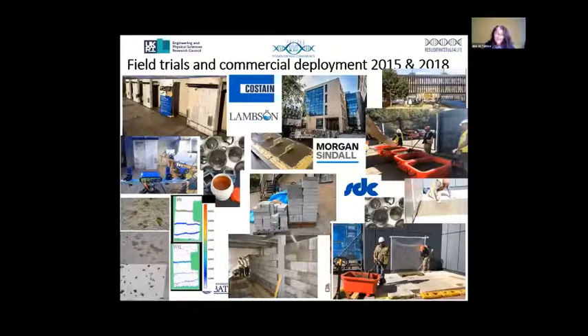We carried out two commercial deployments. So again, back in 2015, one of them was part of the new extension to our Department of Engineering, Cambridge. And working together with the contractor, Morgan Sindall, we produced 200 concrete blocks to replace commercial ones. And these were made with a range of different self-healing materials and products, including mineral additives and encapsulated agents, as well as a range of low carbon cements. And we recently performed non-destructive testing on those blocks.